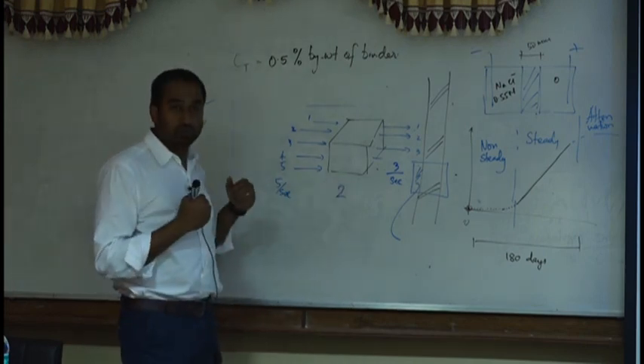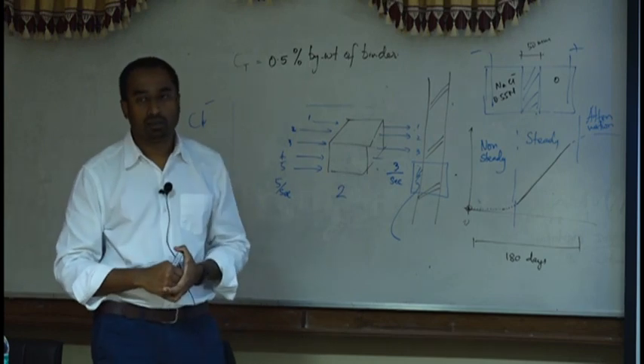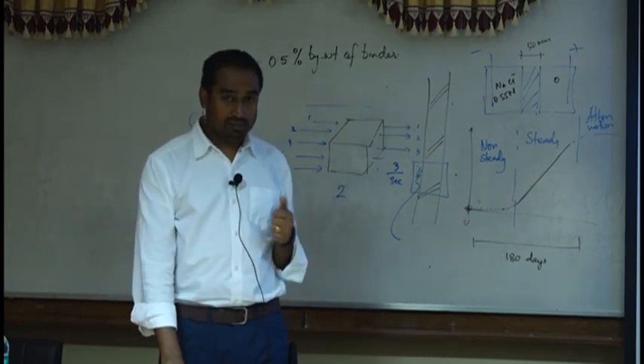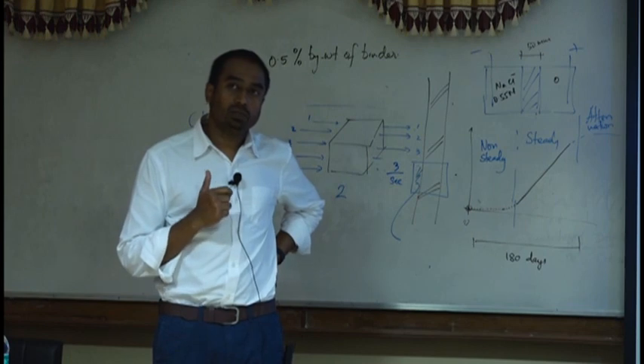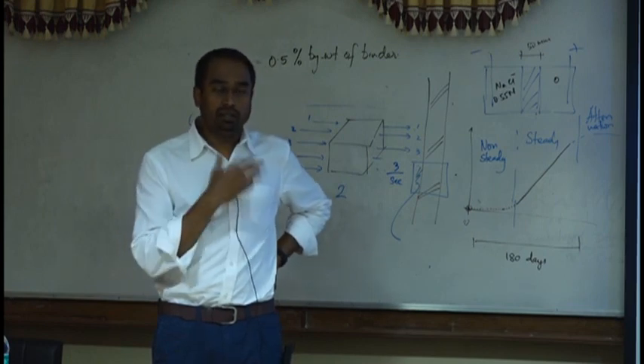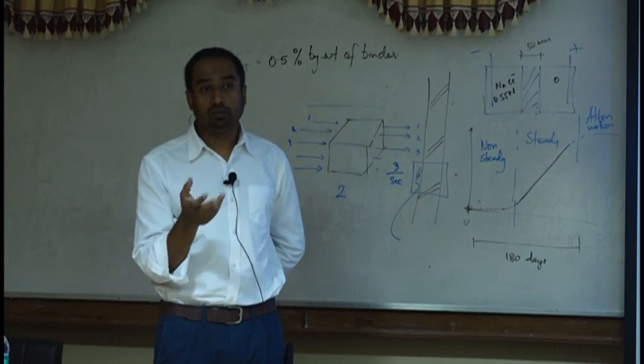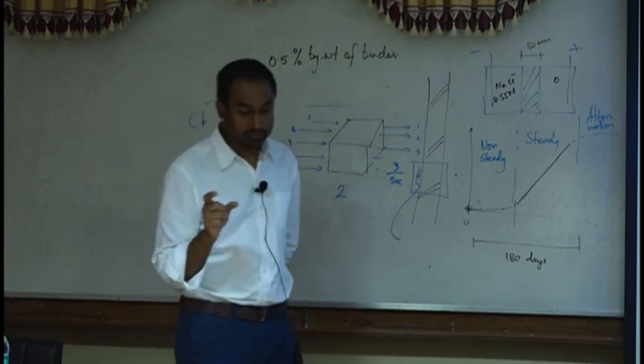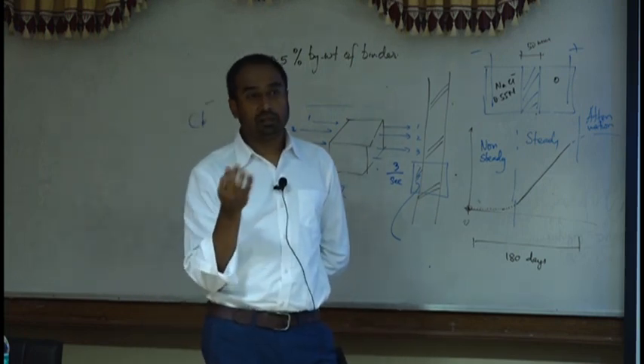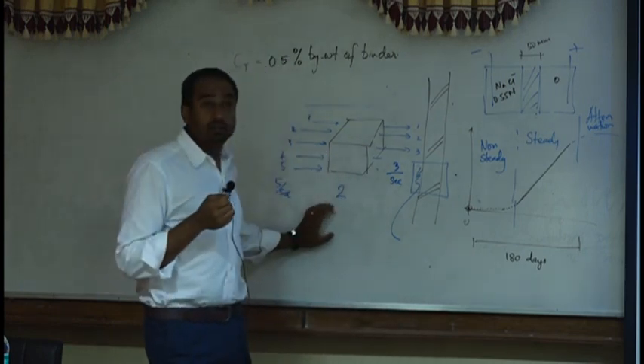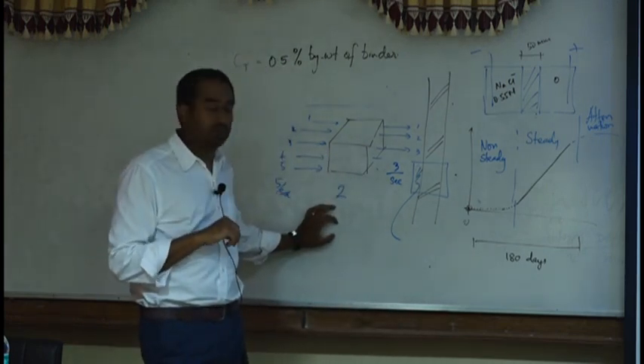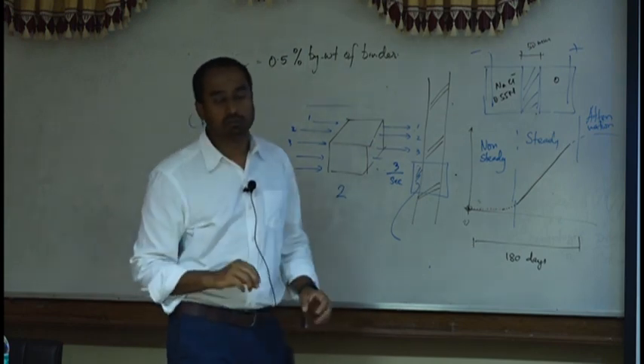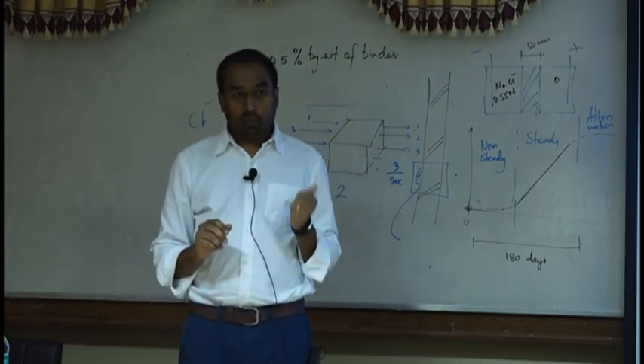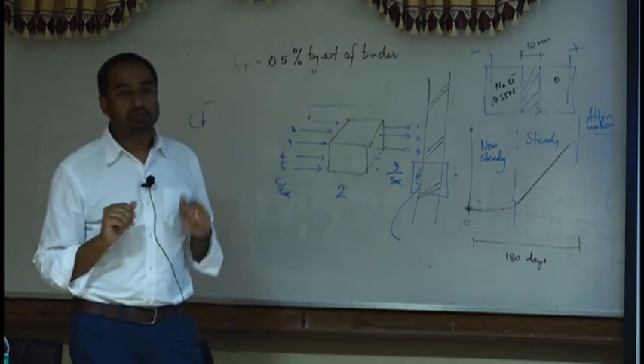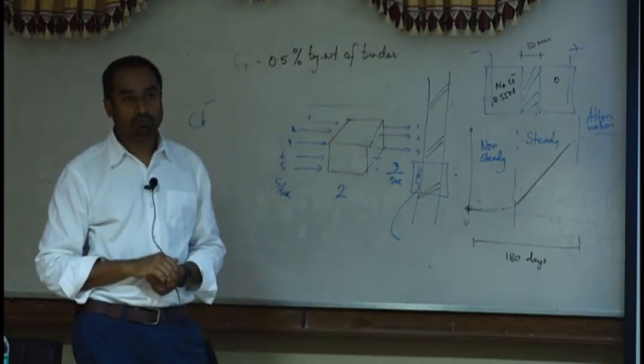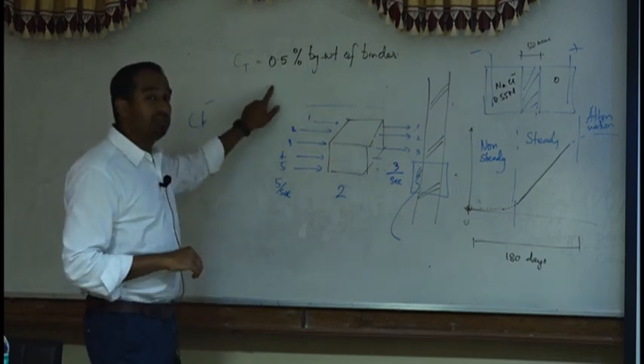Binding refers to flow and the reaction part of the flow. Okay. They are distinctly different. So any replacement material with a high volume of aluminates or extra calcium silicates, so GGBS, PFA, metakaolin, any of them, will have a higher binding capacity than Portland cement, because of the fact that they have aluminates and other things. Portland cement might have a higher threshold. So the threshold might be higher for Portland cement.